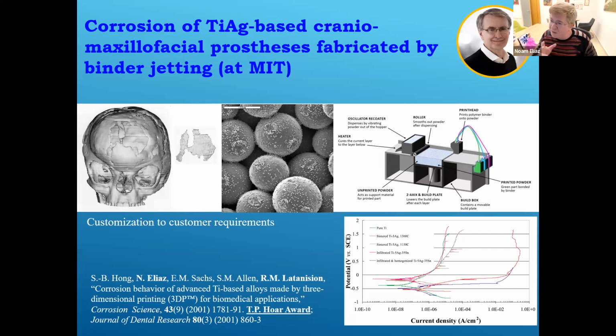Typically, the minimum wall thickness is around 1 millimeter, as it was in 2001, according to the Ashby materials selection book. And with additive manufacturing, in this case binder jetting, as a rule of thumb, the minimal thickness that you can get is 10 times the diameter of the powder. And since you can use very fine atomized powders nowadays, you can easily get much lower than 1 millimeter and customize it on demand. So this was a collaboration at the time with people from Harvard dental school and others.